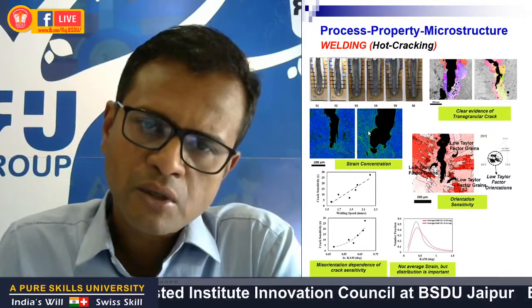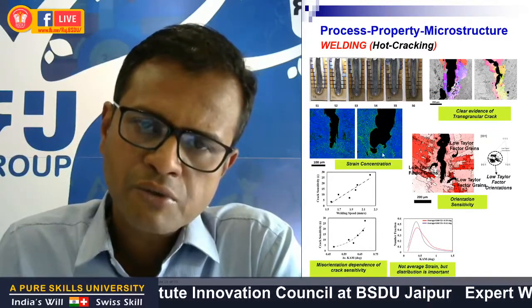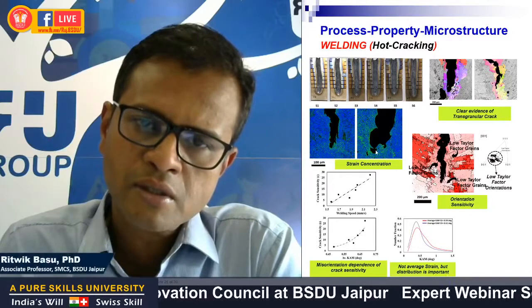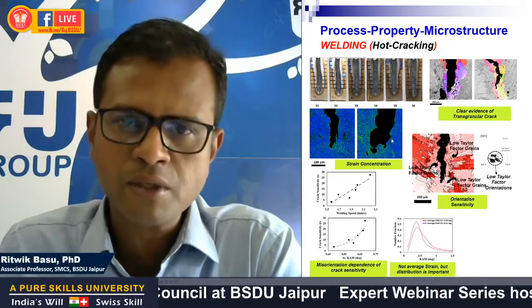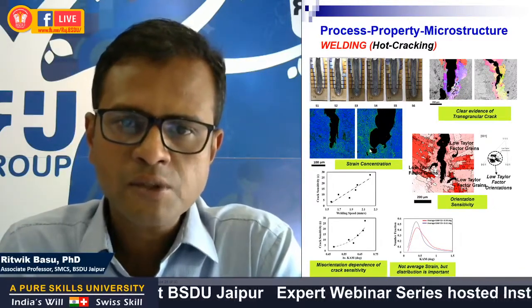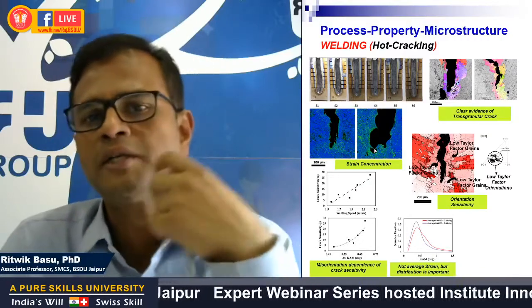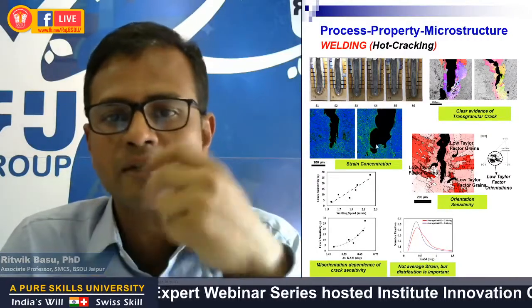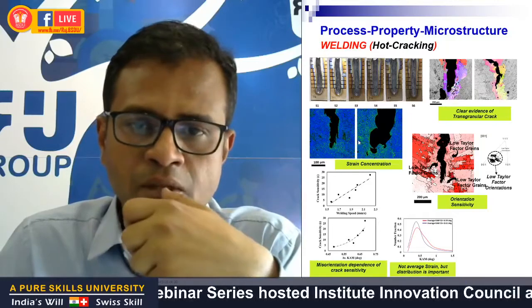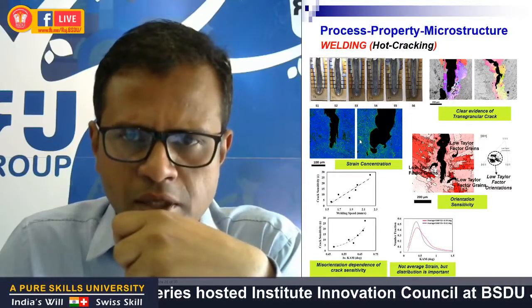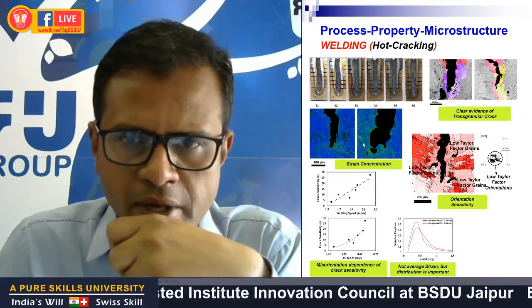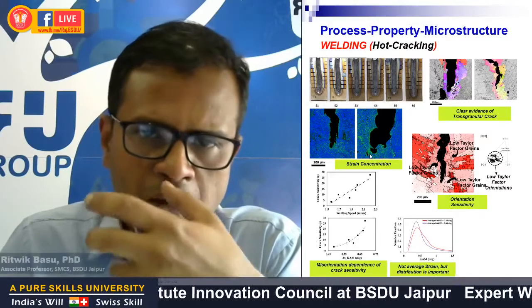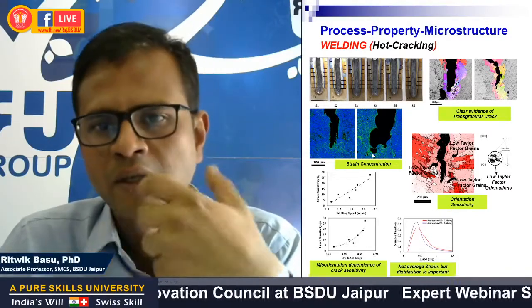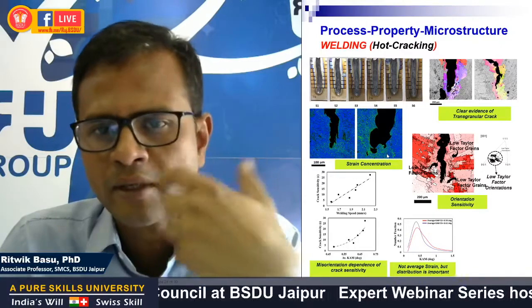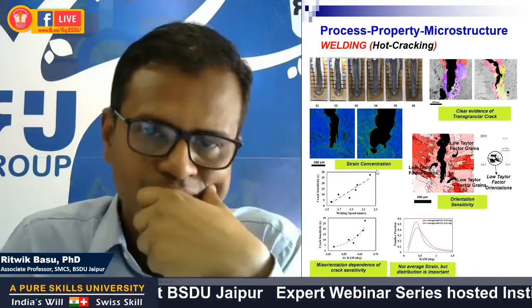So it was also brought out that a higher strain concentration was seen to be associated around the cracks with increasing propensity, and this was verified through the local misorientation distribution that shows significant heterogeneity between these samples. So these local misorientation points, as could be seen in green color, were accumulated more at the subgrain boundaries that were primarily the low angle grain boundaries.